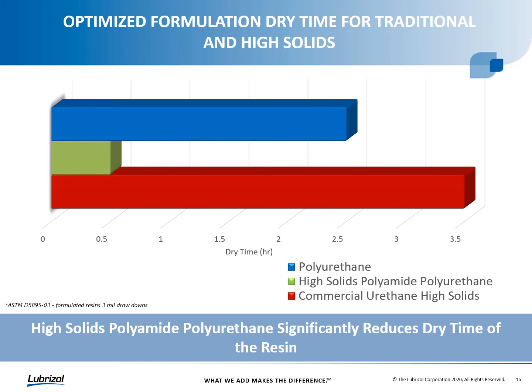And in some applications, if that dry time is a little too fast, this resin is quite flexible, so you can slow that dry time down with the addition of some things like humectants or glycols, or even just adding a small, like 1 or 2% of water if you were formulating up around 40% solids. If you drop the solids down a percent or two, you can also increase the open time as well to kind of dial that in for your particular application.